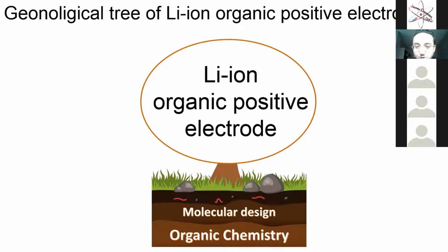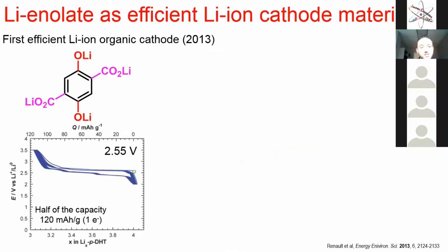I mean, to be used as a lithium ion organic positive electrode. So the first efficient reported lithium ion organic dates back to 2013. It was published by Poizot's group, and it's a very efficient molecule. Below you have the cycling curve of this molecule, so it's perfectly reversible, and it has a low polarization, and the potential is 2.55.